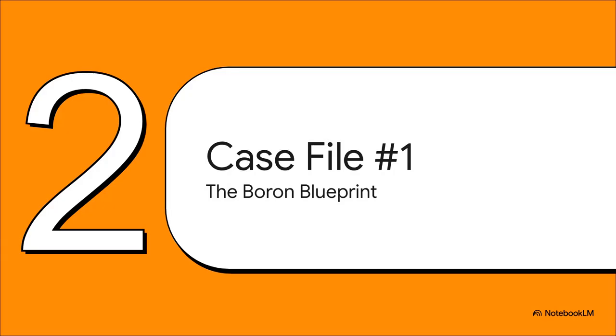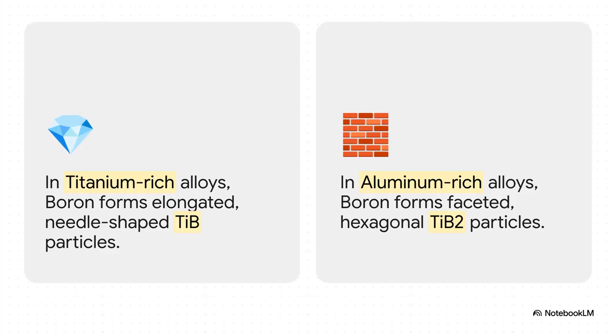All right, let's open up our first case file, the boron blueprint. What exactly is going on when you add this element into the mix? So the first big clue they found was that boron is a bit of a chameleon. It doesn't act the same way every time. See, in alloys that had more titanium, it formed these tiny needle-shaped particles. But in alloys with more aluminum, it formed these blockier hexagonal particles. So the main recipe of the alloy actually changes the shape of the reinforcements.